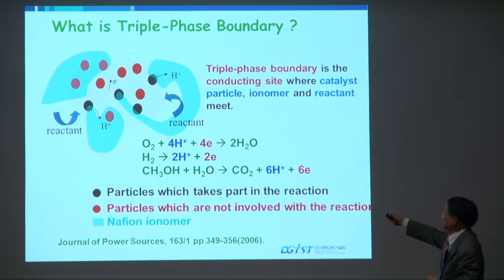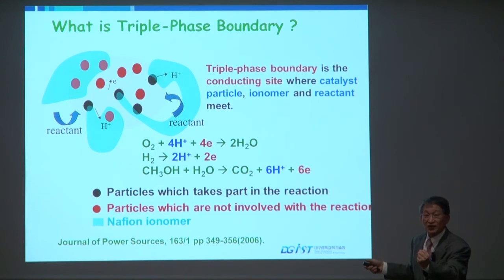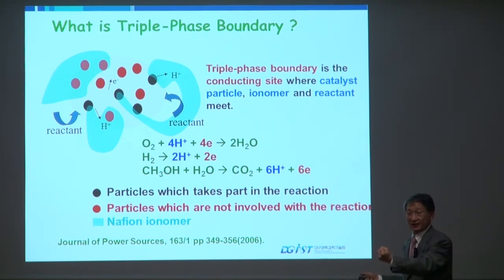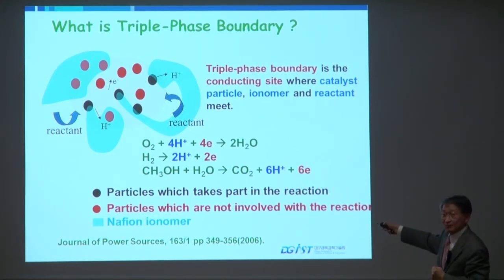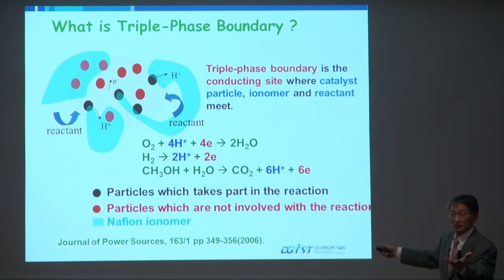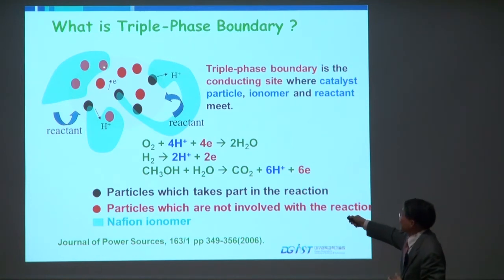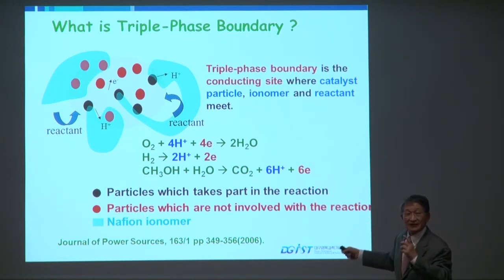That means the catalyst layer needs a suitable electron conductivity, and carbon can provide this very well. And carbon nanotube, graphene, which is a much better conducting substrate, produce higher activities. And also, at the same time, for proton conductivity, you need ionomers, so Nafion polymers. So the catalyst with carbon and Nafion together acts most actively for the fuel cell applications.